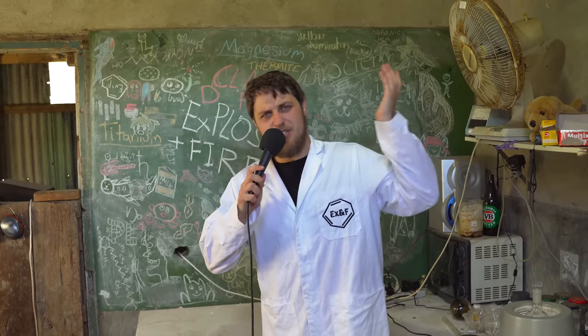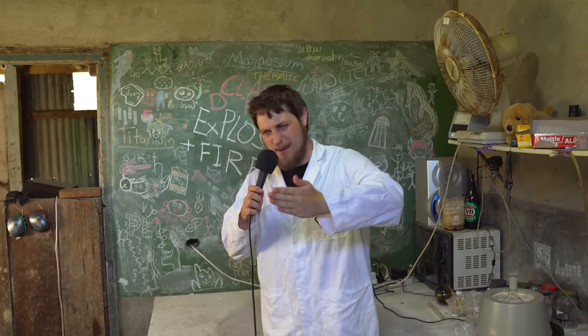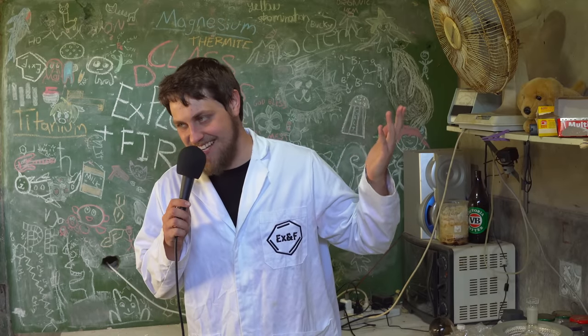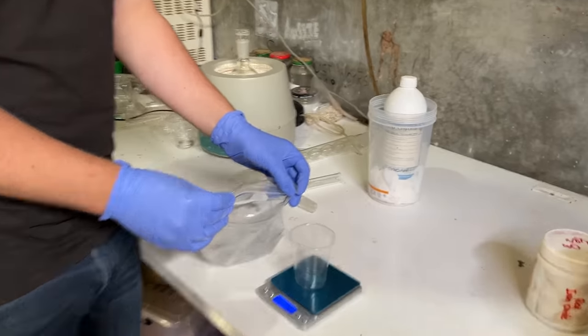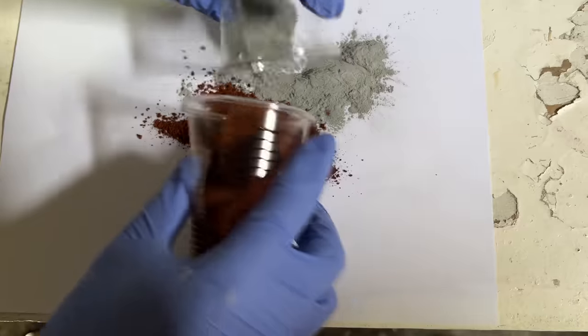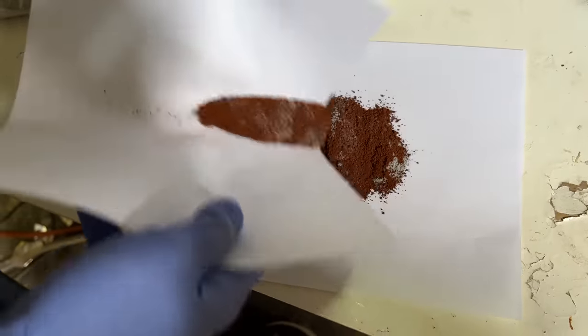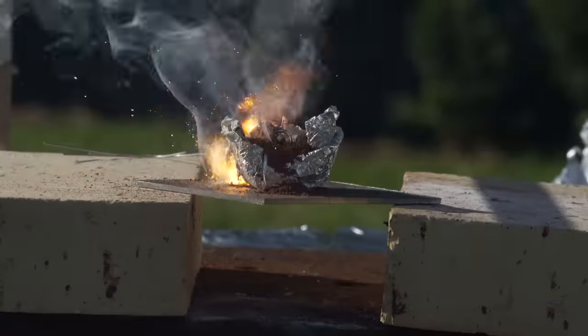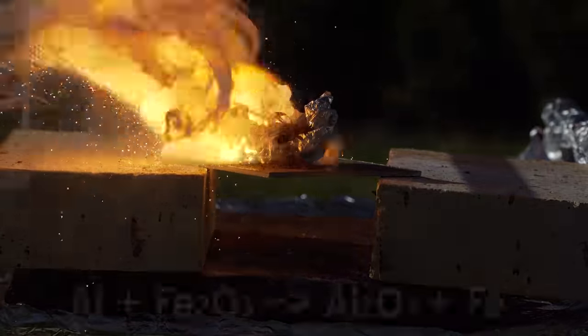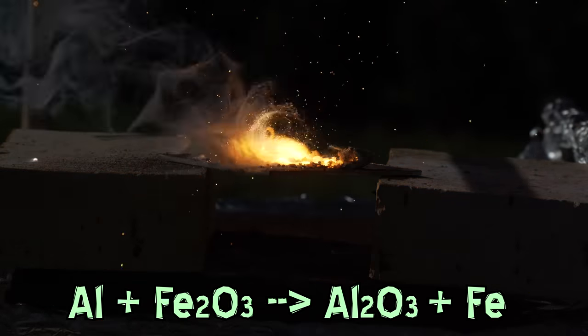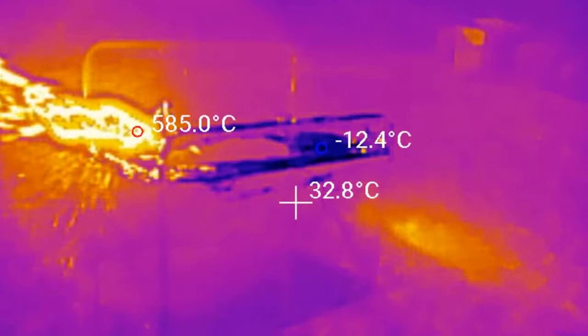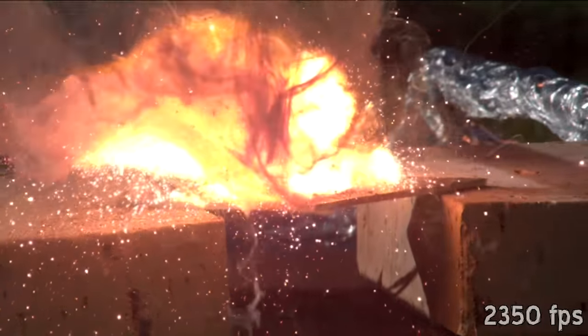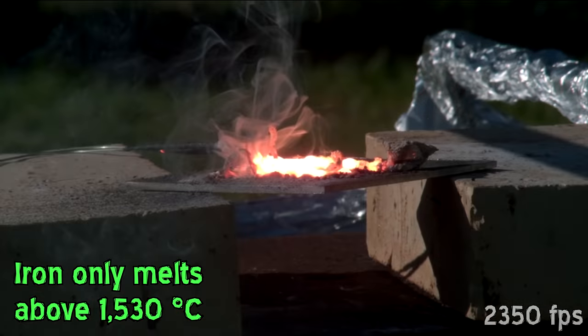How do we set titanium on fire? Rather than stepping through different blow torches and gases, let's immediately jump to extreme measures. If we're talking generating extreme temperatures, my thought immediately is thermite. It's just a mixture of iron oxide and aluminium. What's significant about thermite is that there are no gases generated in the reaction — in most pyrotechnic reactions you generate hot gases which disperse and send heat away, but in thermite the reaction product is molten iron which retains all the heat, and the aluminium oxide forms molten slag. But the thermite on the titanium plate does not light it on fire at all — apart from all the molten iron sticking to the plate, the plate is completely fine. We weren't able to damage it even remotely with the thermite.